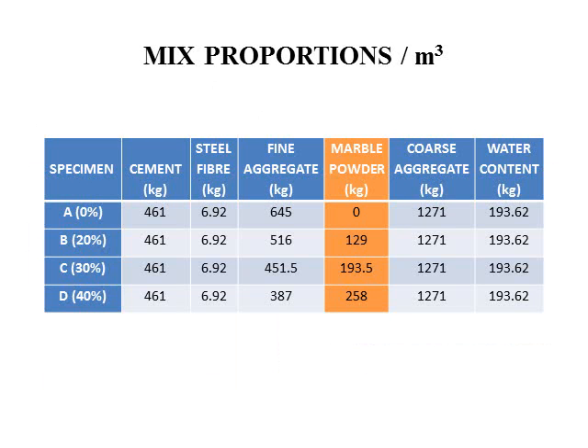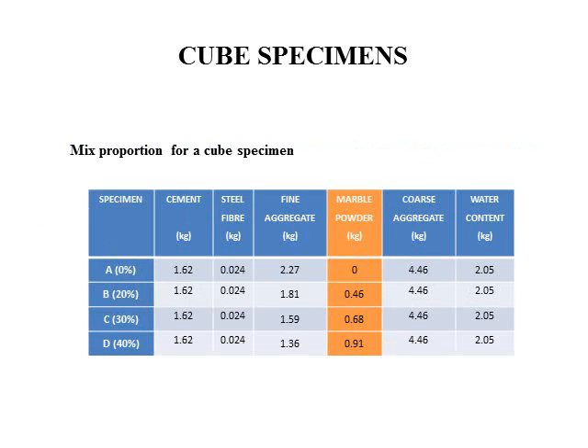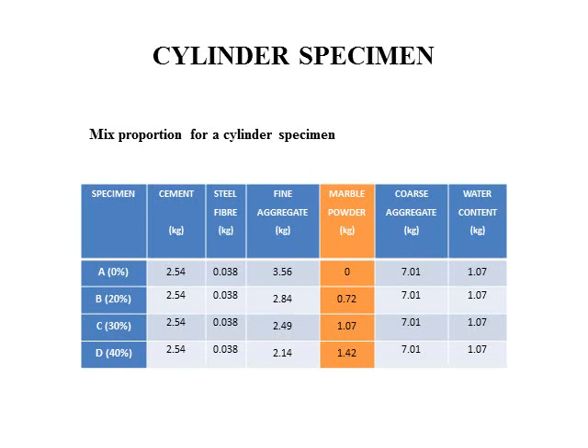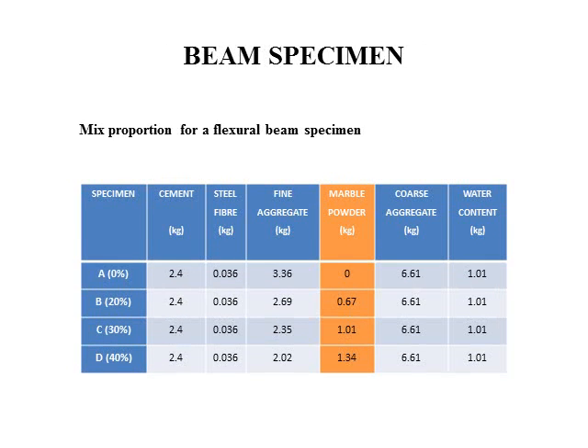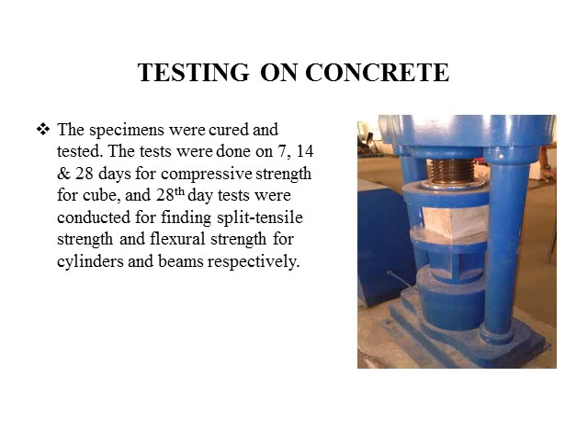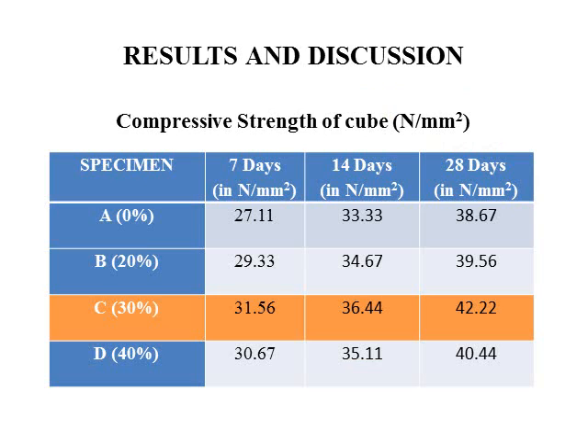The specimens are cast for 7, 14 and 28 day testing of cubes. The mix proportions per meter cube are shown, and this is for a cube specimen. For a single cube specimen the mix proportions are shown. For a single cylinder specimen the mix proportions are shown, and for a single beam specimen the mix proportions are shown. Testing. The concrete was cast and cubes were tested for 7, 14 and 28 days, and the cylinder and the beam were tested for 28 days.